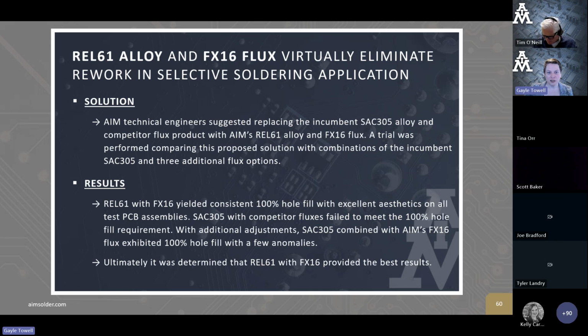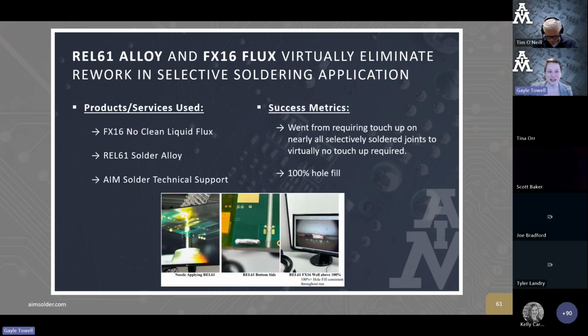So we had a technical engineer help them out. They tried out the combinations of the incumbent SAC305 and REL61 with the incumbent flux and the FX16 flux. What performed better overall was the combination of REL61 and FX16. They got 100% hole fill. So they went from 100% touching up everything to 100% hole fill, which is a pretty dramatic improvement. Our flux with the SAC305 did cause improvements as well, but that combo of the flux with our REL61 gave the best results overall. So again, touching up everything to touching up nothing is a pretty dramatic change.